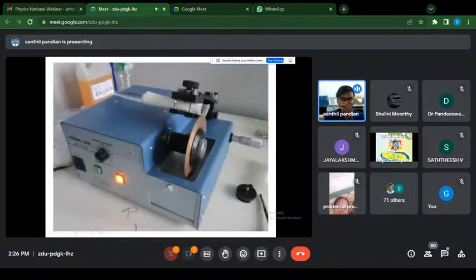So this is the 20 centimeter long TGS crystal. This is the diamond coated wheel cutter, and ethylene glycol is kept inside this tray in order to avoid the formation of thermal stress in the grown crystal. This is a speed controller. So first, before we go for crystal cutting, you have to identify the mechanical stability of your grown crystal, using Vickers microhardness measurement, whether it is a mechanically low, stable, or moderate hardness material, or a very high hardness material. You have to confirm. Then you have to increase or decrease the speed of the diamond wheel cutter.